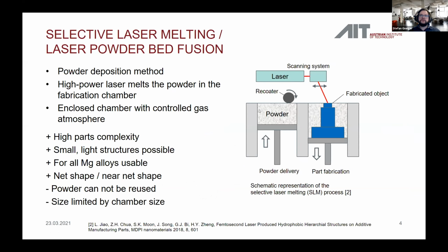I will keep this short, as maybe some of you already know this, but I will start with the selective laser melting, or the laser powder bed fusion. It is a powder deposition method where a high power laser melts the powder in the fabrication chamber, where the part is then produced. This is in an enclosed chamber with a controlled gas atmosphere. With this process, you can build parts with a high complexity, with very small structures, so lightweight parts are possible. This process is usable for all magnesium alloys, and net shape or near net shape parts can be produced. The disadvantage is that the powder cannot be fully reused, and the size of the parts is limited by the chamber size.